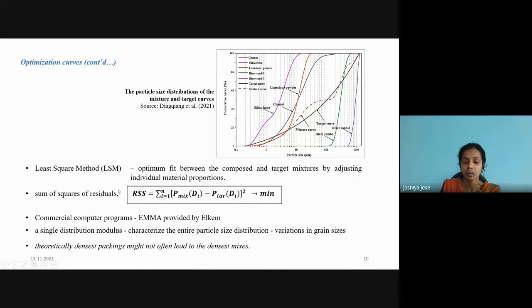Different commercial computer programs, for example, EMMA provided by Elkem, can be utilized for this purpose. But this method also has a disadvantage: a single distribution modulus is used to characterize the whole particle size distribution. And this can cause variations in grain sizes, because the grain sizes can differ, and the theoretically densest packing might not often lead to the maximum packing in the actual case.